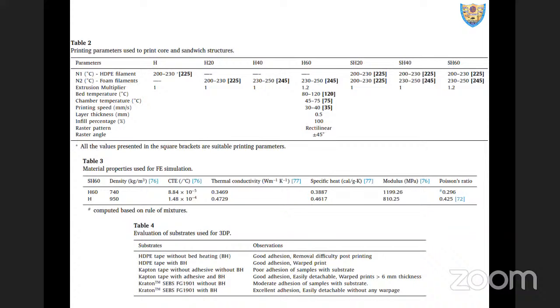So with HDP filament and H20, 40, 60 foam filaments, based on the different parameters, we need to freeze suitable printing or processing factors for realizing HDP with 20% glass microballoon, 40%, 60% microballoon, or even the sandwiches. And this table shows the range of values we used for finding the suitable parameters. And what is that suitable parameter we found is in square brackets. Whatever material properties we used in FE simulation are also presented here.